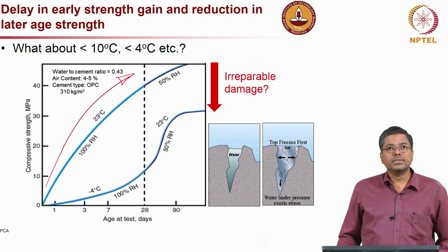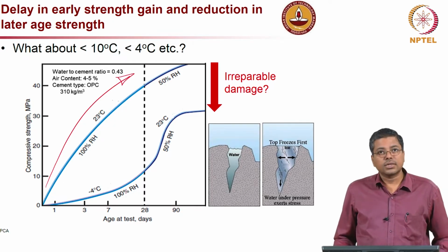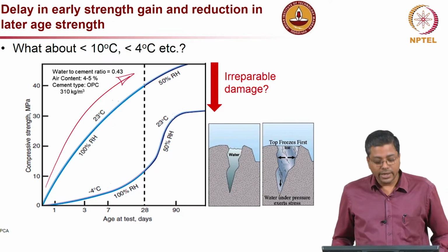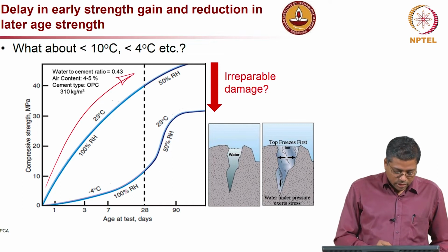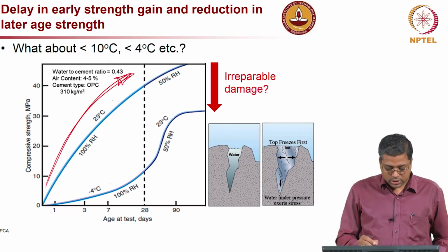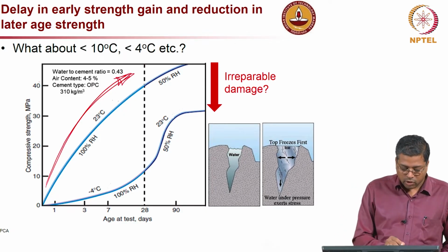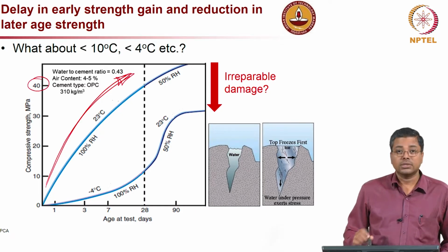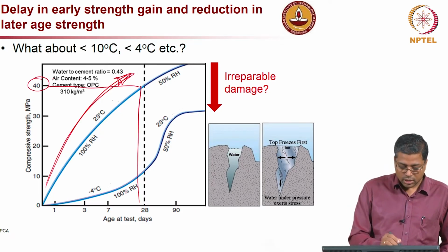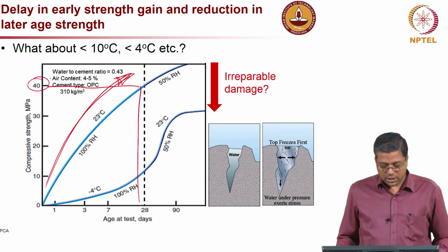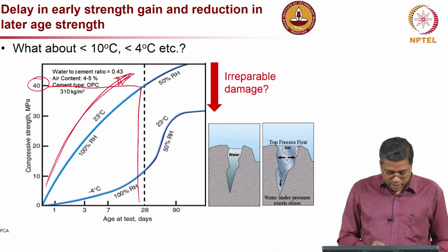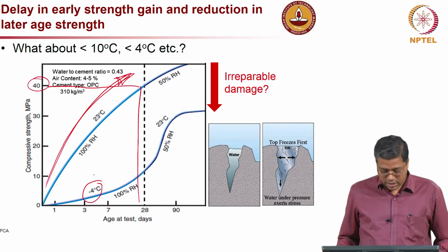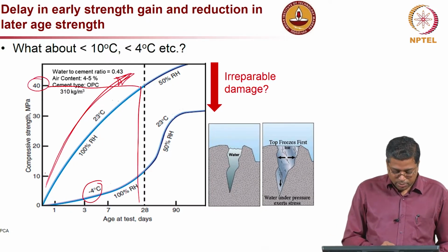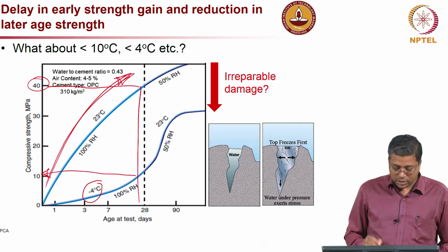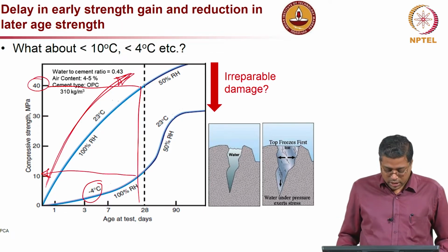Okay, now let us look at delay in the early strength gain and reduction in the later age strength. So, this graph, the top graph, shows strength gain of about 40 MPa in 28 days, which is this line here. You get about 40 MPa, but the same concrete, when the ambient temperature is minus 4 degrees Celsius, gains only about 10 MPa strength in 28 days. So, significant reduction in the strength.